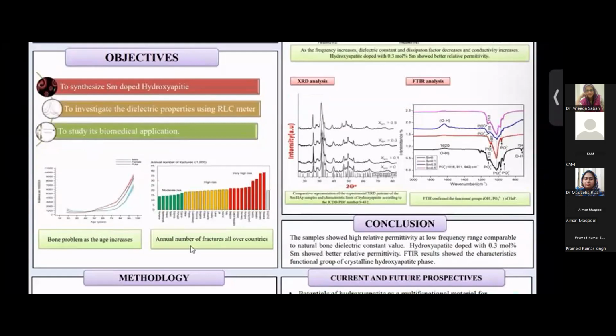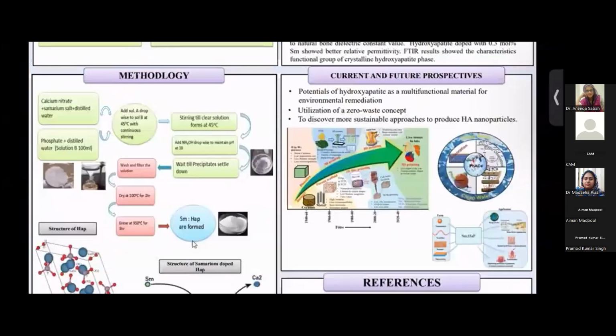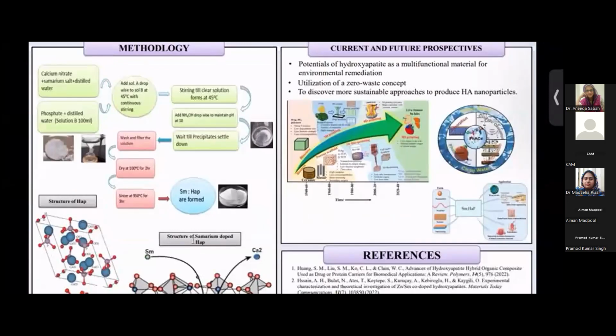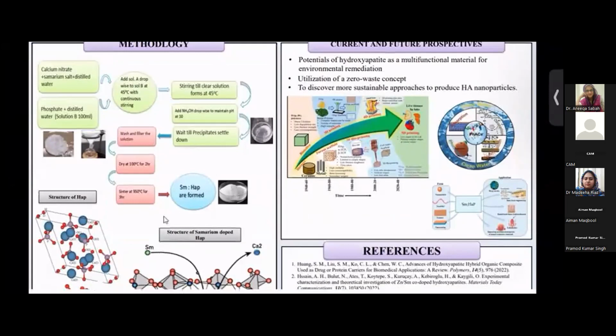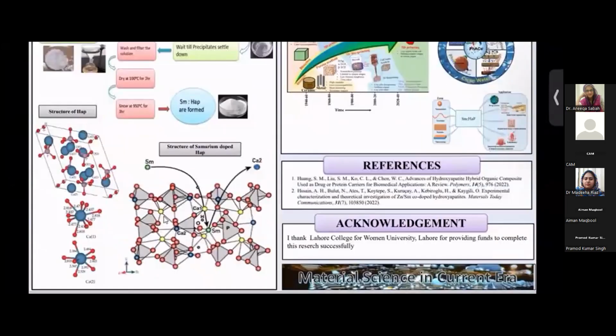Therefore, hydroxyapatite is used as a biomaterial because it has great biocompatibility with natural bones. Samarium is doped with hydroxyapatite to improve its properties. Samarium-doped hydroxyapatite was synthesized using the co-precipitation method. This flowchart represents how samarium-doped hydroxyapatite was synthesized. Now the structure of samarium-doped hydroxyapatite: there are two calcium sites, calcium 1 and calcium 2. As the ionic radius of samarium is larger, it is substituted at the calcium 2 site.